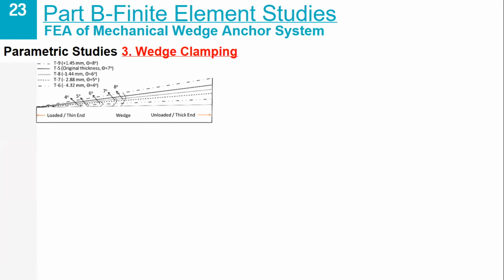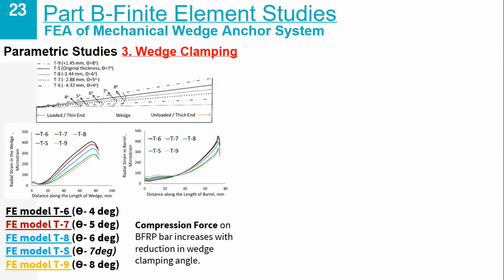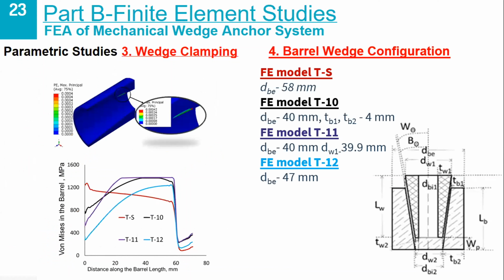The third parameter is the clamping angle of the wedge. So 5 different clamping angles have been investigated, and we found that the compression force on these BFRP bars increases with the reduction of the clamping angle. So that is another observation that we made. So this black line is the one with the least clamping angle. So that has the highest compressive stress, or the radial stress, on these BFRP bars. So this is critical because as we mentioned, the transverse strength of these BFRP bars is very low compared to the longitudinal strength. And finally, the fourth parameter that has been investigated is the barrel wedge configuration.